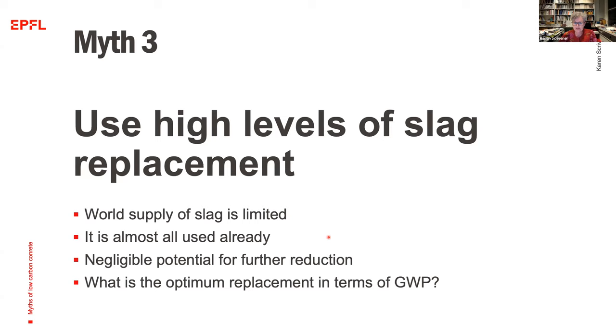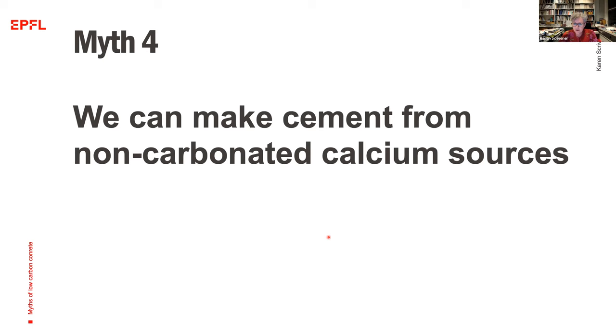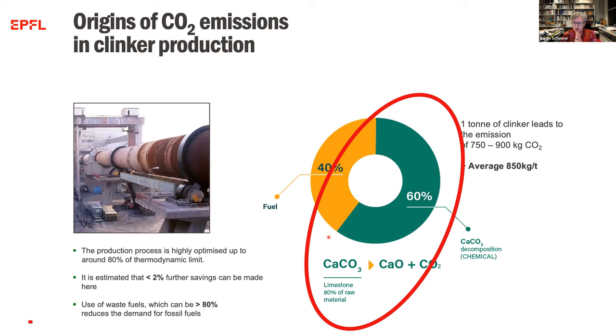So the fourth myth, which is gaining a lot of popularity at the minute, a lot of venture capitalists are investing in this idea, is to say, can we make cement from non-carbonated calcium sources? Now, what do I mean here? Well, if we look at the CO2 emissions from cement, we see that about 60% of those emissions come from the breakdown of limestone. So limestone is calcium carbonate, which is about 80% of the raw material. And during the production of cement, this breaks down to calcium oxide, which goes on to form the clinker minerals, and CO2. So if you see this, you say, well, can we use something other than limestone?